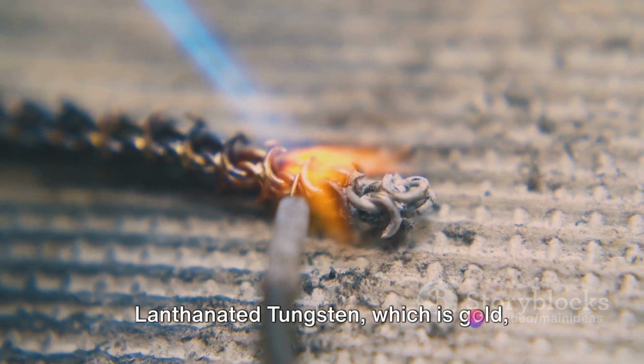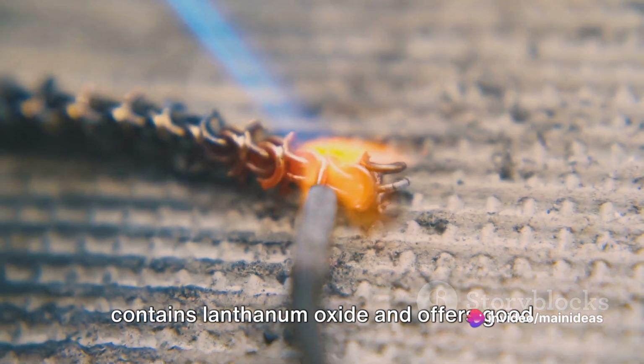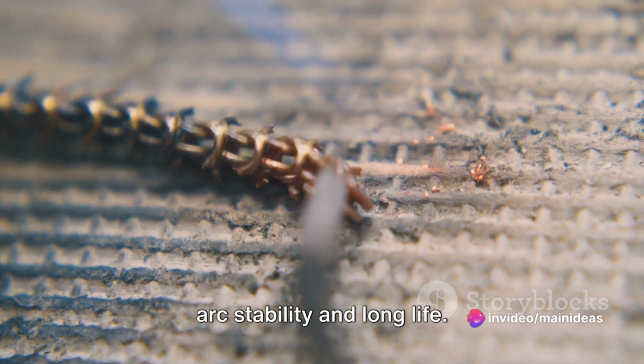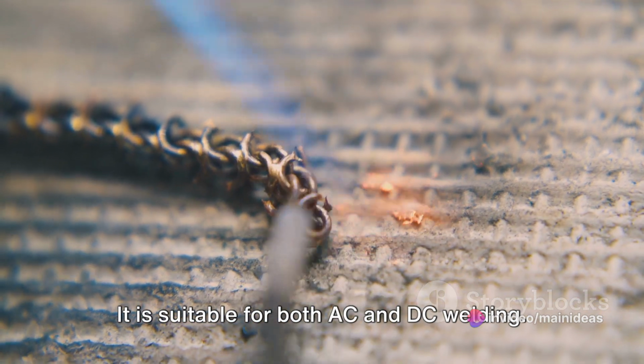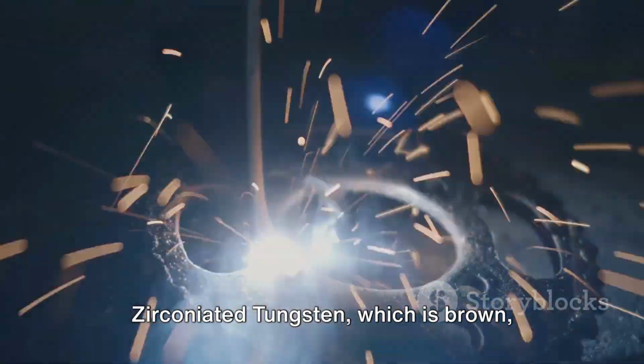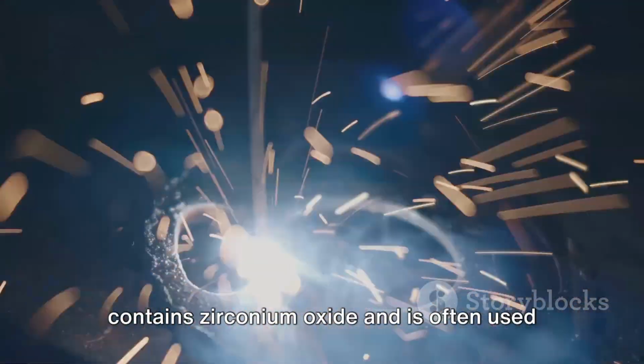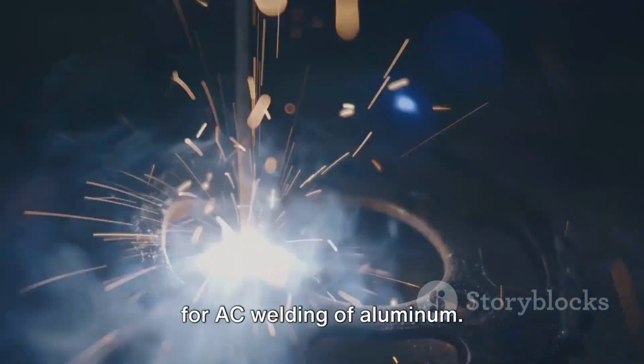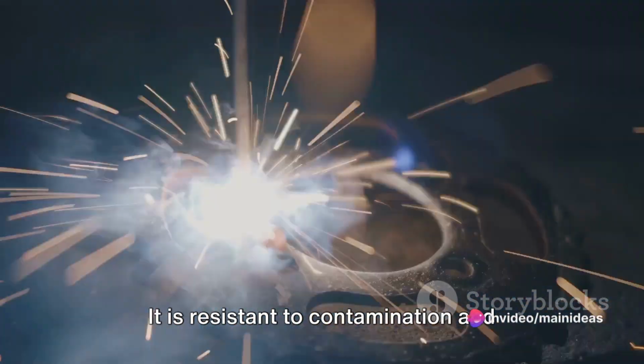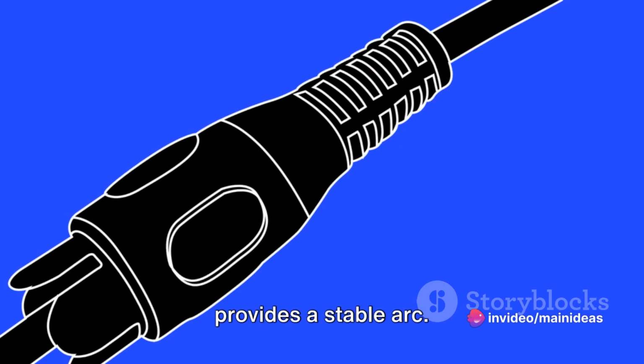Lanthanated tungsten, which is gold, contains lanthanum oxide and offers good arc stability and long life. It is suitable for both AC and DC welding. Zirconiated tungsten, which is brown, contains zirconium oxide and is often used for AC welding of aluminum. It is resistant to contamination and provides a stable arc.